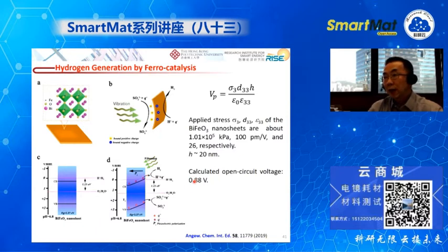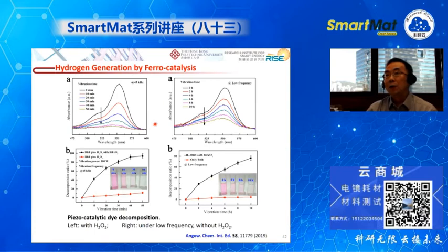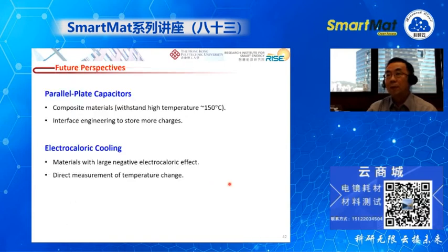we do a detailed calculation. We found the open circuit voltage for this nanosheet is 0.88, and there is a chance for the tilted band edge to be more negative than the hydrogen evolution, and therefore the hydrogen evolution is possible. And we also tried the dye decomposition of this material, and it also shows effective dye decomposition.